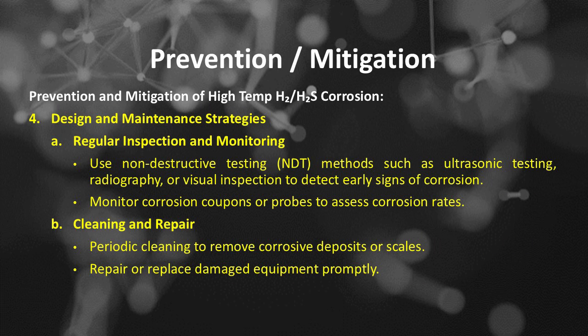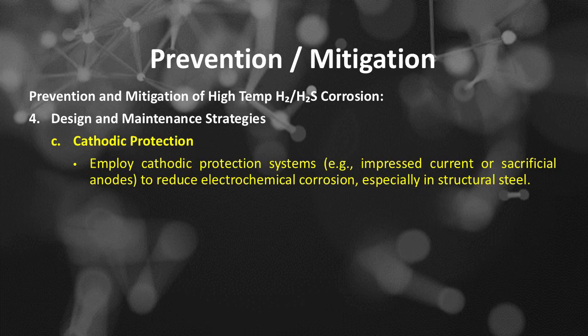Number 4 of prevention and mitigation methods is design and maintenance strategies. A: regular inspection and monitoring. Use non-destructive testing, NDT, methods such as ultrasonic testing, radiography, or visual inspection to detect early signs of corrosion, monitor corrosion coupons or probes to assess corrosion rates. Number B, cleaning and repair. Periodic cleaning to remove corrosive deposits or scales, repair or replace damaged equipment promptly. Number C, cathodic protection. Employ cathodic protection systems, such as impressed current or sacrificial anodes, to reduce electrochemical corrosion, especially in structural steel.